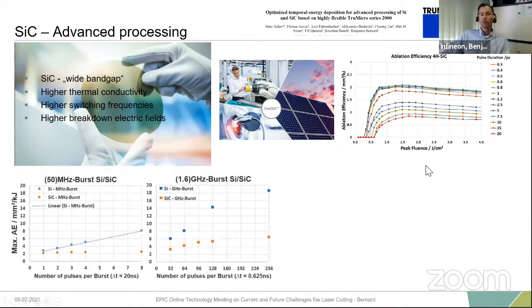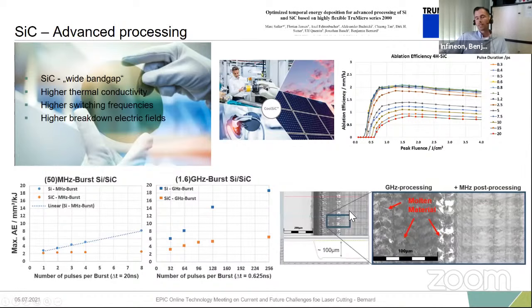And we also had a deep look into the megahertz and gigahertz burst, because there was a lot of discussion that gigahertz burst is something very interesting. What we find is that the ablation rate can be scaled up. That means compared to single pulse or to megahertz burst, we have a higher ablation rate. We found that on silicon as well as on silicon carbide. But the quality was much decreased. It behaves like a nanosecond application more or less.